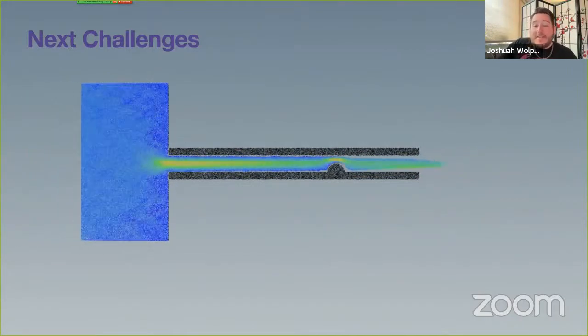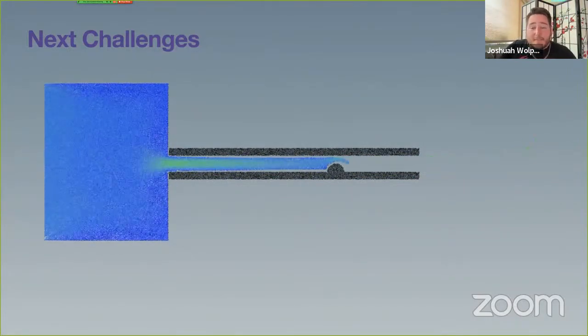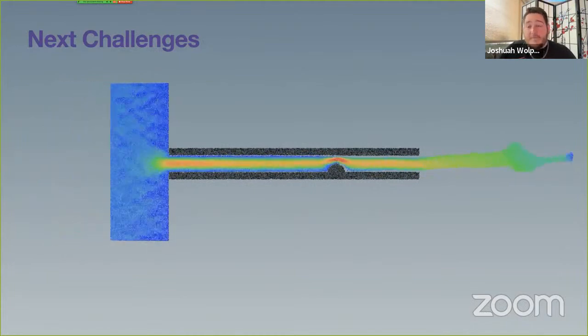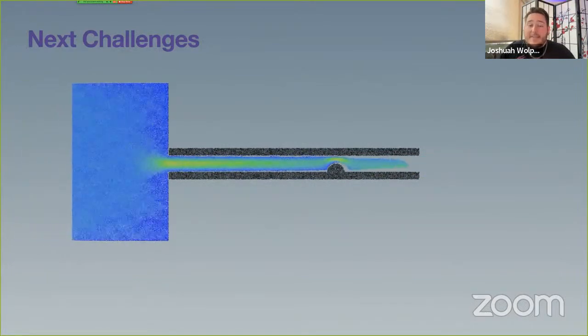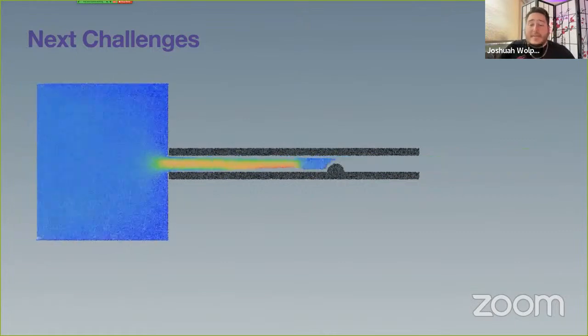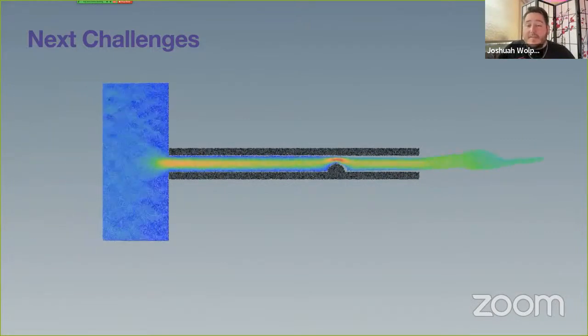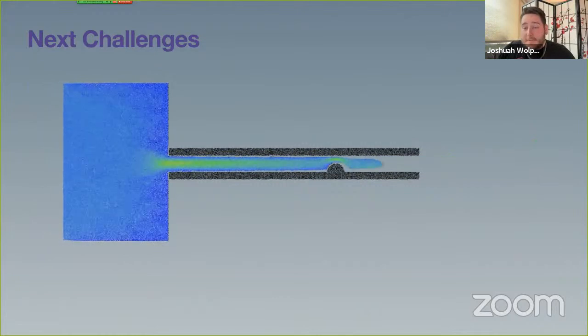The first has to do with the inevitable case where a grid node is marked as separable, both from damage gradient partitioning and from solid fluid coupling. And in this case, perhaps a three-field approach could work, but this causes the contact normals to be much less clearly defined, so this easily requires further study.